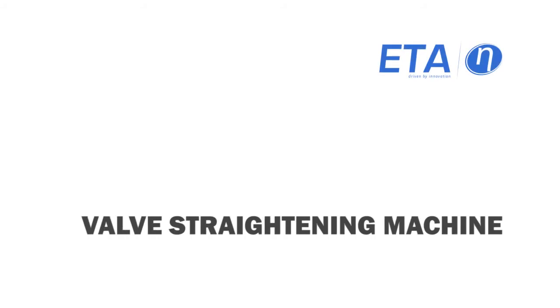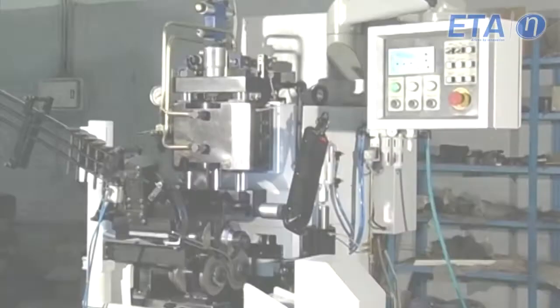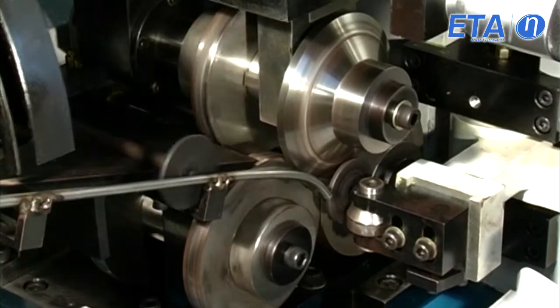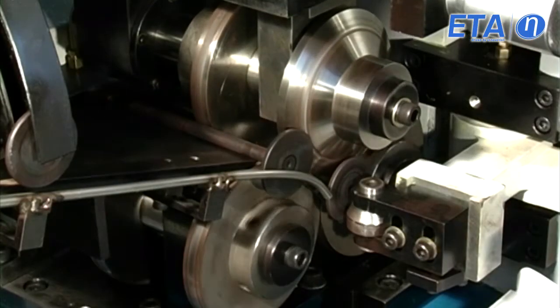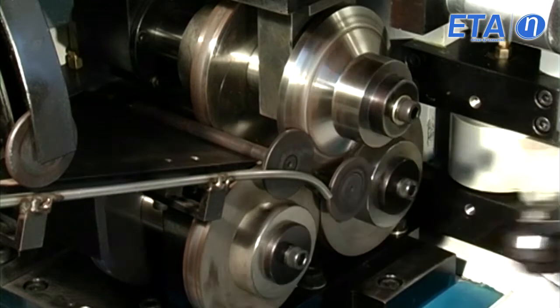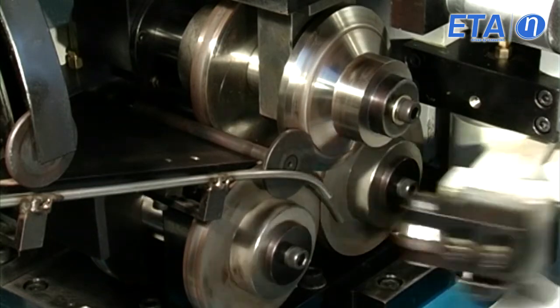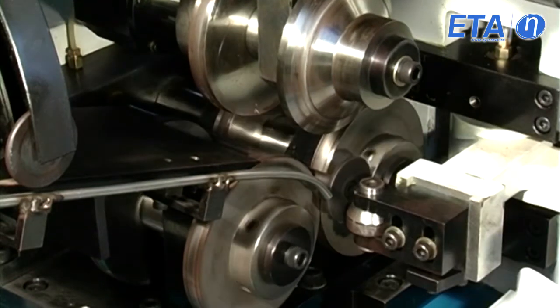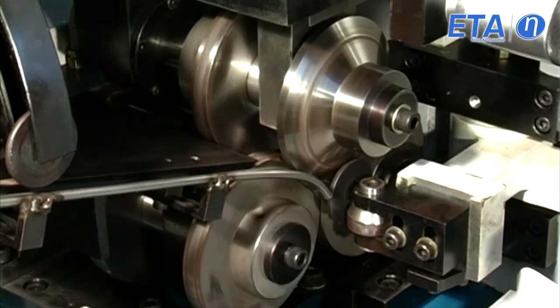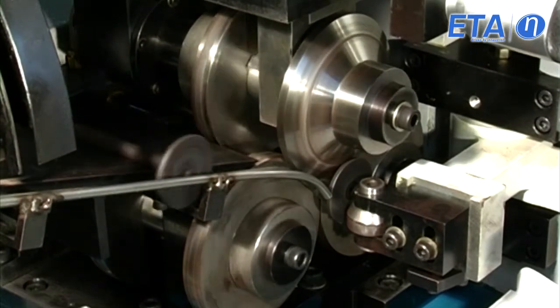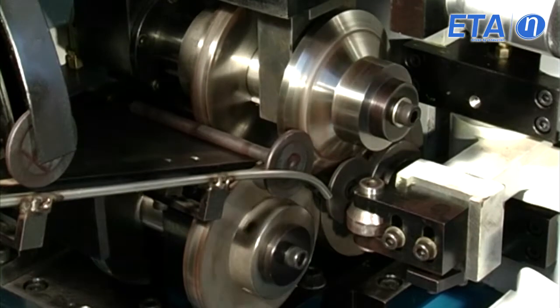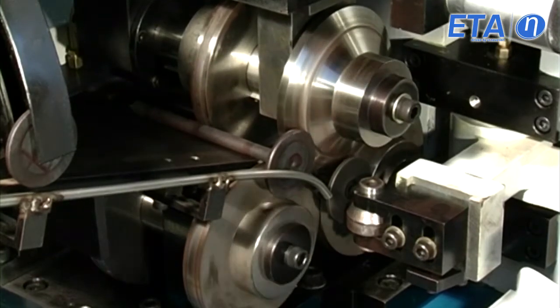Valve straightening machine. We manufacture a range of straightening machines of various sizes to cater to stem dia of 4 to 22 mm. Cycle time is as low as 5 seconds depending on the diameter. The stem is straightened to 0.05 mm and the head within 0.08 mm.